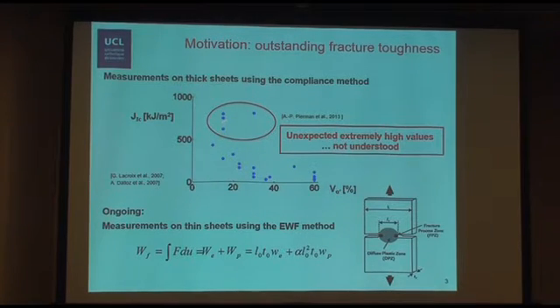Another important piece of information about those steels: those measures here have been taken on thick sheets of about 10 millimeters thickness using the compliance method, whereas I'm more focused on thin sheets, since it is thin sheets that are of interest for the automotive industry. And in that case, there also exists a method to quantify the resistance to the propagation of a crack called the essential work of fracture, the EWF method, and that takes place on such a DENT sample. I've also put the equation, but I want to explain the methodology because I don't have results yet, but it's ongoing, and it is to validate this conclusion of very high fracture toughness for plate-like microstructure steels, but on thin sheets this time.